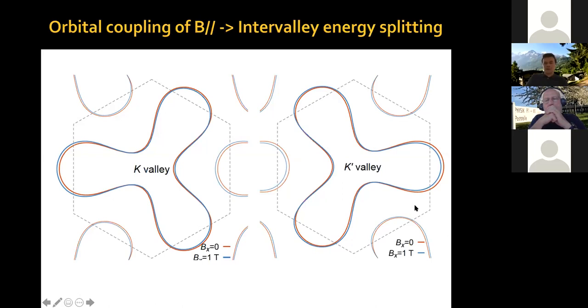Now, of course, as I mentioned earlier, you could have, for example, strong strain in your system that leads you to choose this particular direction, and there's a particular nesting for this direction, etc. But it would be very strange that the direction of your nematic director could slowly vary with charge density, as we see that it does.